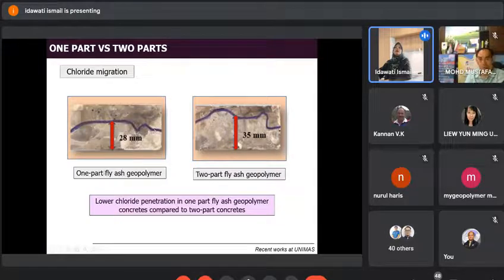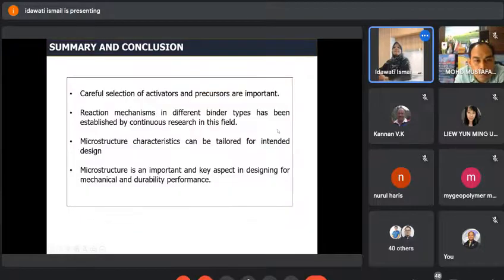So something can be done again to study how we lower the chloride penetration in the system. This is specifically for our fly ash in Sarawak. Maybe it works better for other fly ash in other parts of Malaysia or elsewhere. So lower chloride penetration in one part fly ash compared to the two parts concrete. So in summary, based on these two main ingredients, we need careful selection, okay, of what is your activator, what is your precursor, and then the reaction mechanism of different binders